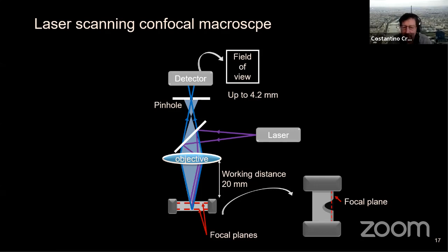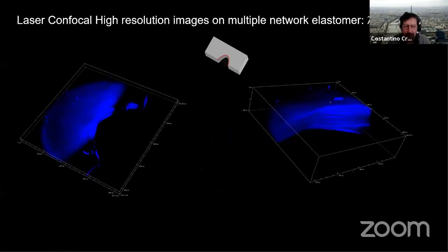So anyway, you can put your sample flat on the surface as shown here, and then you put it under the microscope, you can stretch it, and you can do some imaging. These two pictures here are images taken at two different magnifications of the same sample. This sample contains a sacrificial bond. So it's one of these multiple network samples that has many chains designed to reinforce the material. So we have a large detection. This is in a way a tough elastomer, but in this case, we were pretty sure to see something. This is the same elastomer that we used in the Science paper, but now imaged with the fluorescent molecule in a static configuration. So the crack is just being opened, but it's not propagating.